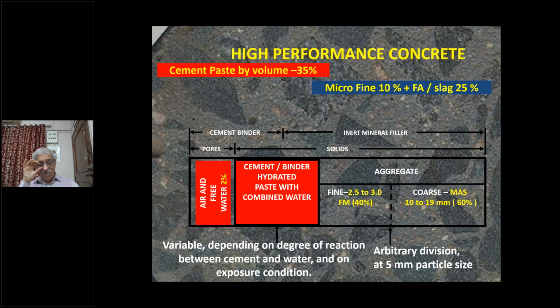Generally, the belief is that oh, fly ash will always give lesser strength, etc. No, nowadays for high performance concrete, the packing of the material in concrete is extremely important. So even if the aggregates are properly proportioned, as they should be, we have to pack the mortar, the binder paste. It has to have fine and ultrafine material both. In addition to cement, you should have slag or fly ash and the microfine mineral admixtures like the ultrafine slag or ultrafine fly ash, etc., or microsilica. These are excellent materials.